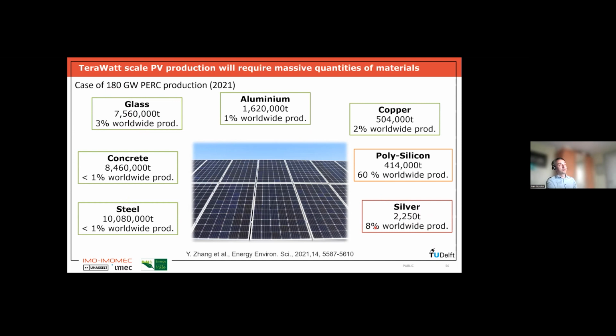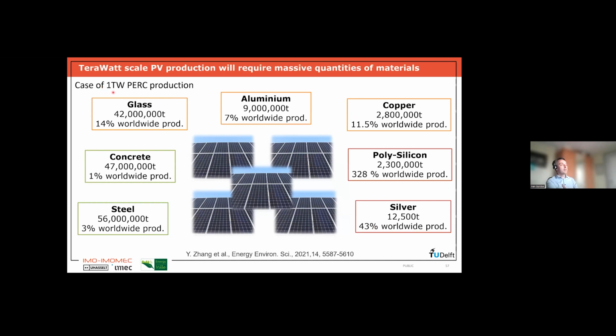Now, if we want to produce 1 terawatt of these materials, which is the minimum we will have to do, it's roughly 5 times more. So we need 5 times more of all these materials, which for silver would mean that we are already around 43% of the worldwide production. So yeah, these become really mind-blowing numbers if you see what is needed. And this is really potentially a problem.